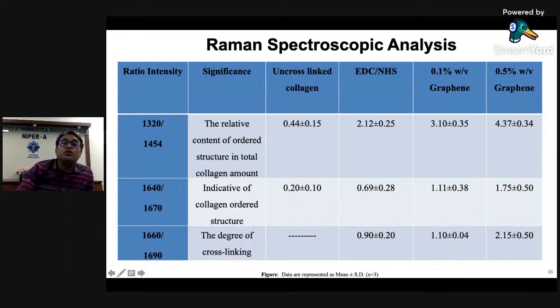Even by looking at this Raman spectroscopy, we can further look into the cross-linking also. For that you need to do the ratio of 1660 to 1690 intensity wave numbers, and then you will see more cross-linking is observed in the 0.5% graphene. So cross-linking and promotion of alpha helical content is actually affecting the mechanical properties of the hydrogel.